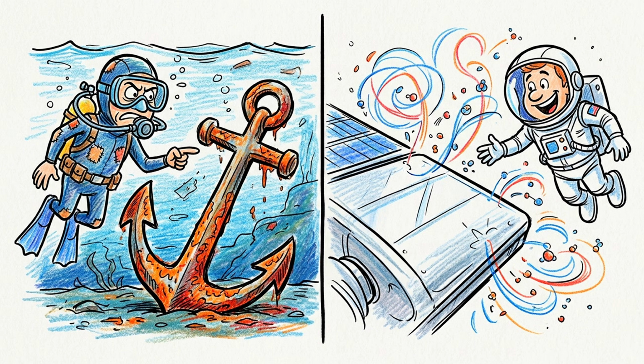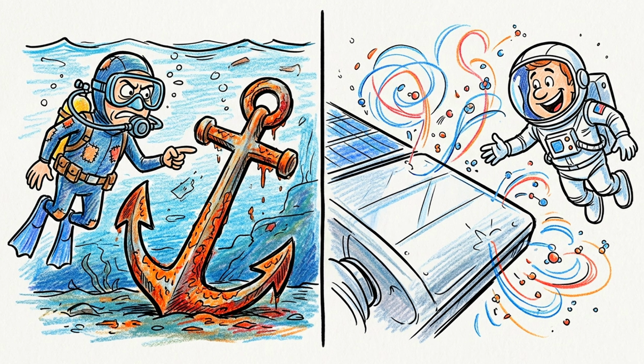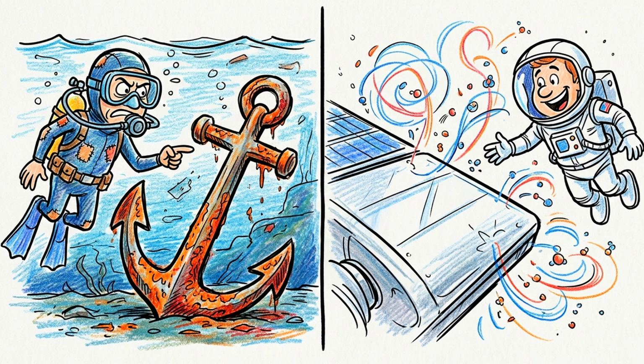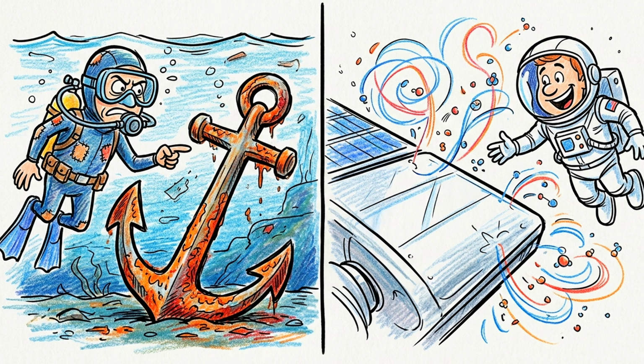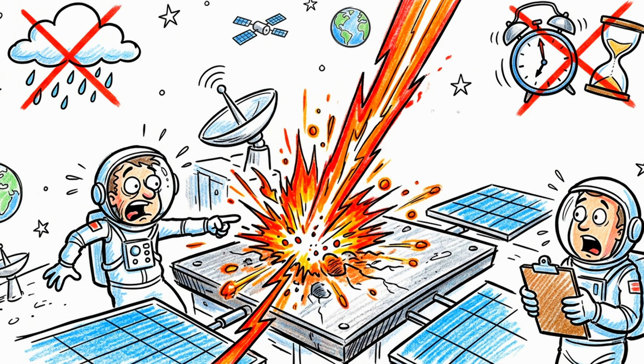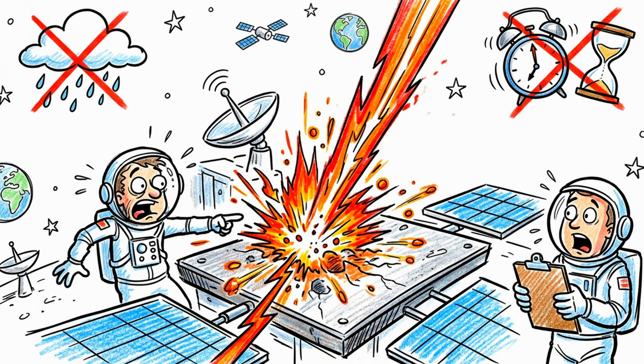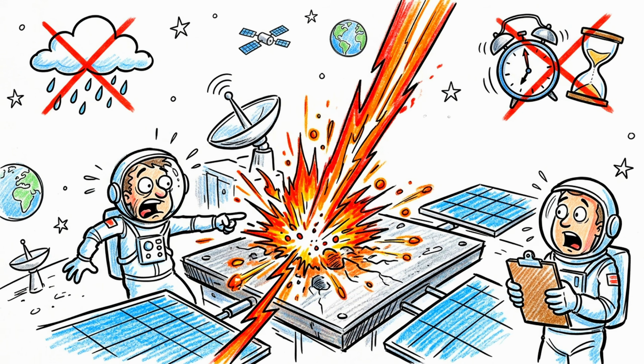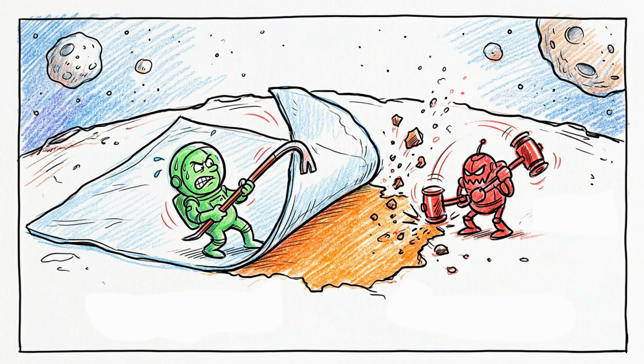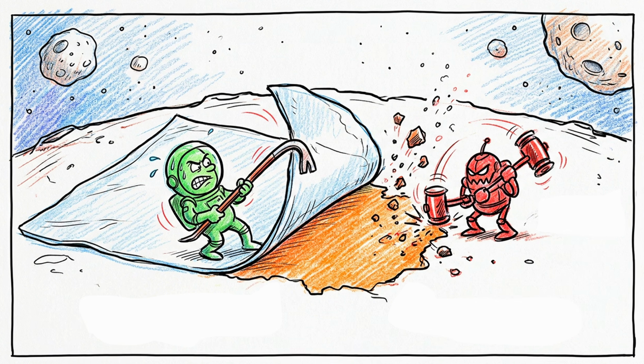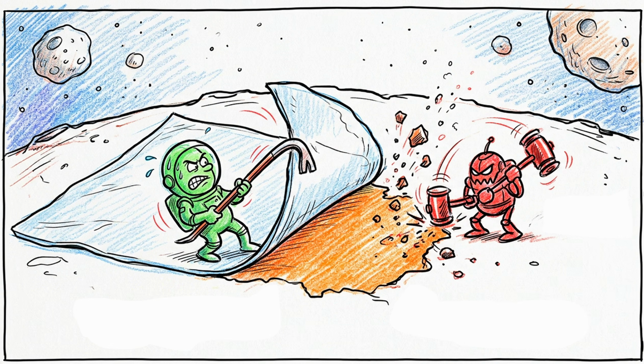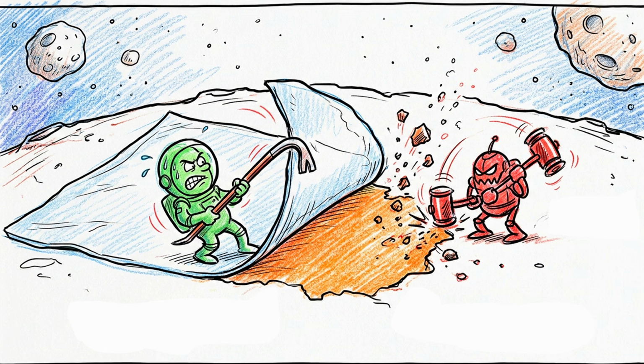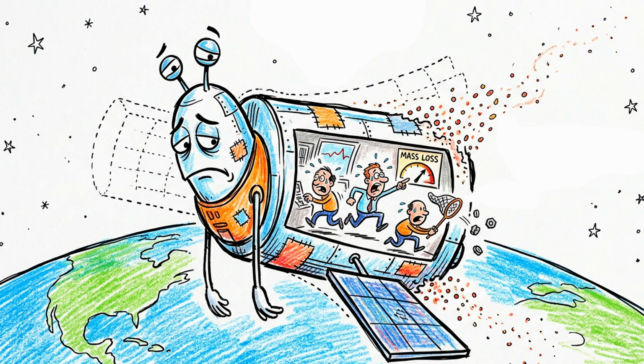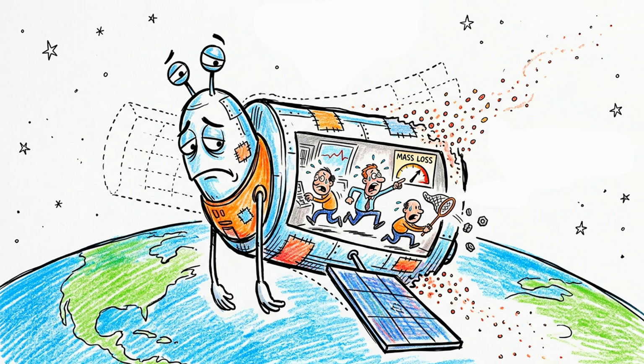The surface does not corrode the way iron rusts in water, where moisture and time and electrical processes work slowly from the outside in. Atomic oxygen erosion does not need moisture. It does not need time to set in. It happens on first contact, it continues on every subsequent contact, and every layer it removes is gone permanently. The mass of the structure goes down as exhaust.